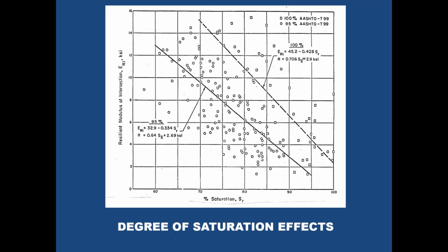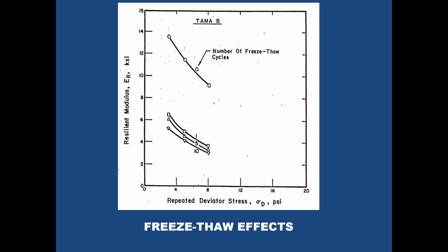Okay, some of the effects that we need to consider. A degree of saturation captures the effect of moisture content on modulus. This is not what you would call a real good relationship. It certainly captures the trend. If they get wetter, particularly on the wet side of optimum moisture content, you're going to lose values on your modulus. Hey, how about a freeze-thaw cycle?